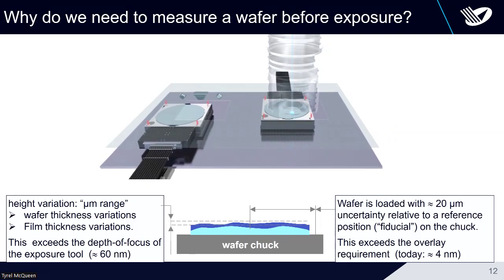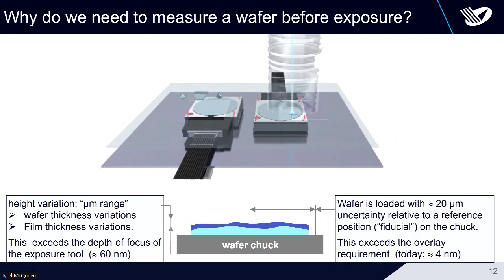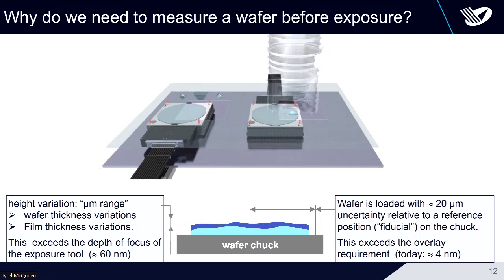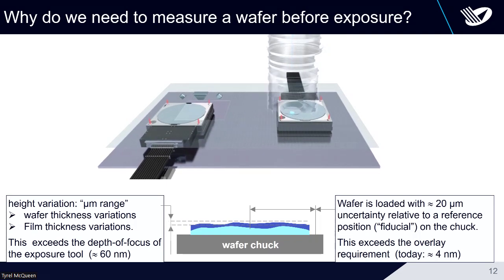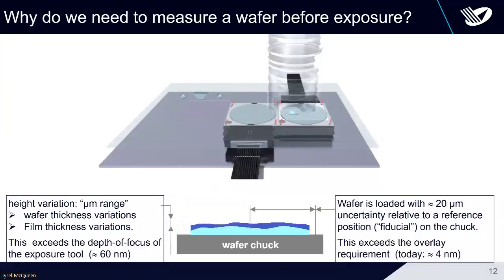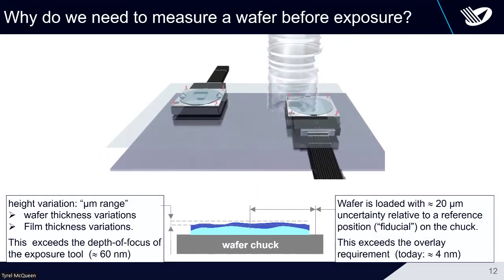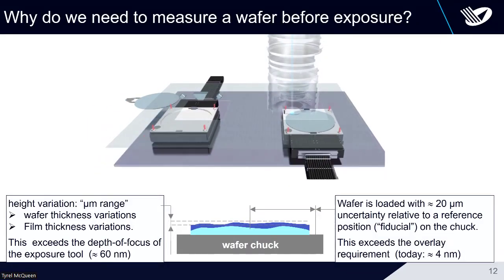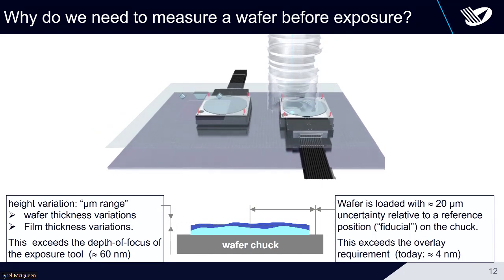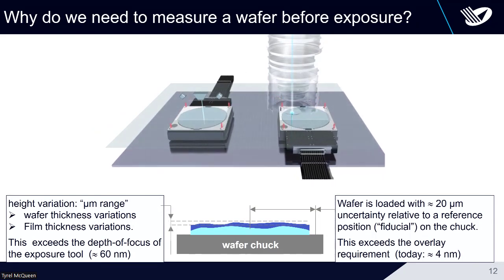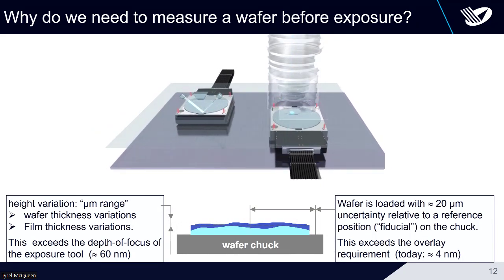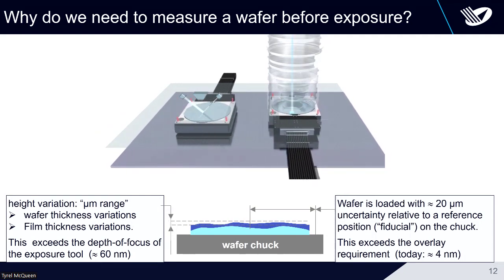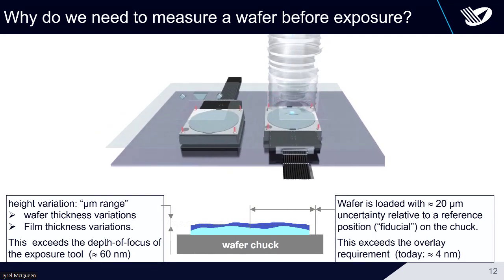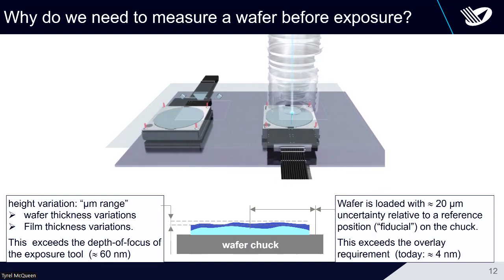That's done at several locations because the wafer is warped. It's not defined by one X, Y, and Z measurement or two. And then once this is done, yes, the wafer is getting shifted over. That must happen very accurately because no new measurement is done. And then the exposure happens. So it's done fully simultaneously, so that there's no time being lost for this alignment and leveling process.